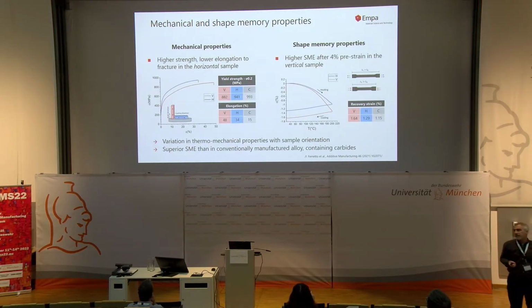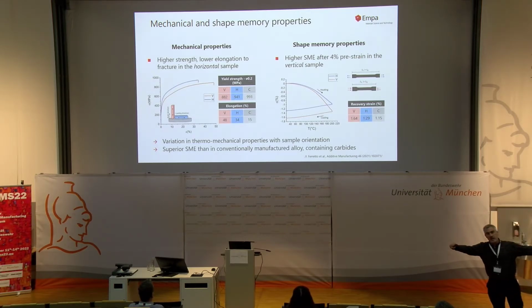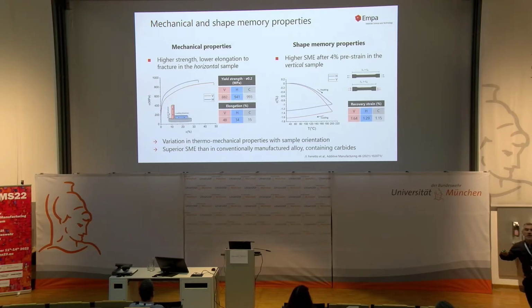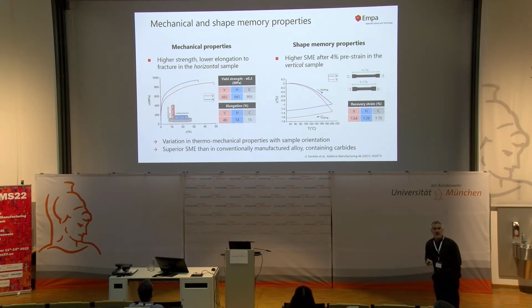But of course we wanted to have a bit more understanding of the mechanical or the thermomechanical properties. And we've created samples in vertical and in horizontal direction. We did tensile tests, and we also measured the shape memory performance. We elongated and we heated to 200 degrees, and we measured the recovered strain. So what you can immediately see is that we do have a strong influence coming from the building direction. Horizontal samples show higher strength as you can see here, lower elongation at fracture. However, ductility is fairly good in the material.